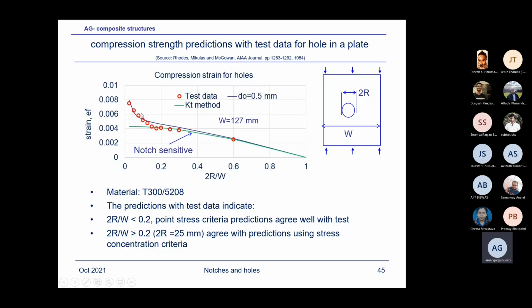As you can see, how beautifully this test data is following the prediction using D naught equal to 0.5 millimeter. And this is the equation based on 1 upon KT. So what I said earlier, that for larger hole sizes, point stress criteria and the stress concentration approach, which is 1 upon KT approach, would predict the same behavior. And that's what you're seeing. So this is based on the test data. So test data really validates this hypothesis, which we are talking about.